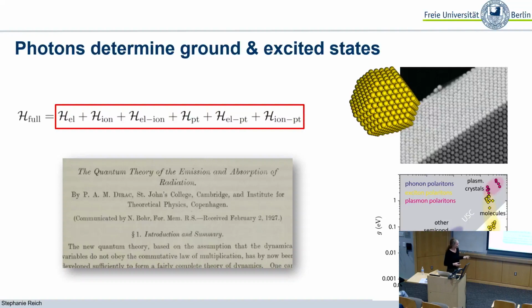It's important because when we went back into the literature and looked at many different excitations that we have in crystals, excitons, infrared active vibrations, plasmons, and so forth, and plotted their light-matter coupling strengths as a function of the excitation frequency, they will be in the ultra-strong or deep-strong regime if they are in this gray shaded area. And what you can see is that this is actually a very common phenomenon for many crystal excitations, that they have an extremely strong coupling to light. It's just something that we haven't really realized so far.